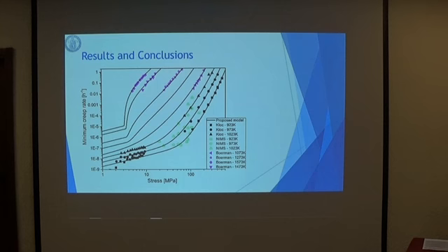So in this plot, we have the proposed model consisting of both dislocational and diffusional contribution. We can see that the trend is consistent with the experimental data. For the ones here on the top, we are supposing that the threshold value will have an important role for the description of the minimum creep rate.